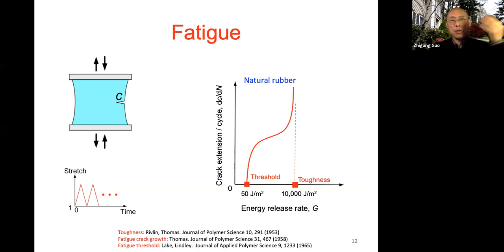This is what mechanical engineers talk about as fatigue. He measured this crack extension per cycle, dc/dN, as a function of G, which is how much load I apply in units of joule per meter squared. If I apply a smaller load, smaller than toughness, then I have smaller growth per cycle. If I make the load even smaller, growth per cycle would be even smaller, maybe 1 micron per cycle, maybe 1 nanometer, maybe 1 angstrom per cycle. But when the load is small enough, the crack will not grow anymore. That's safety. This quantity, called a threshold, for natural rubber is 50 joule per meter squared. The discovery was made in 1965 by Lake and Lindley.